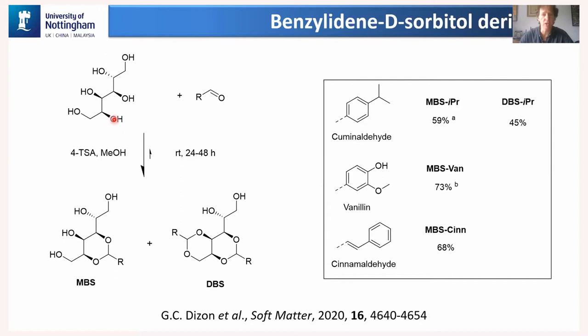And in fact, it's an extremely specific process because of the stereochemistry of these hydroxyl groups. If you look at these, they're both facing in the same direction of that skeleton there, and that makes it a good orientation to be able to react with this aldehyde. So the chemistry is very specific. In the case of vanillin, which I haven't mentioned so far, another natural product, another aldehyde, here you can prepare the MBS derivative again, and in the case of cinnamaldehyde as well. But here the reactivity doesn't work and we can't prepare the dibenzylidene sorbitol compounds.